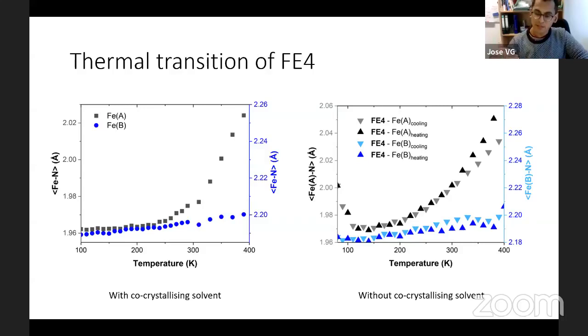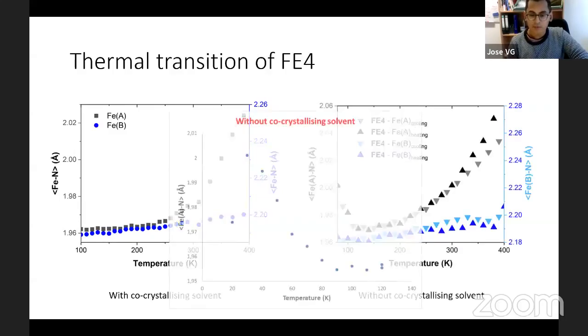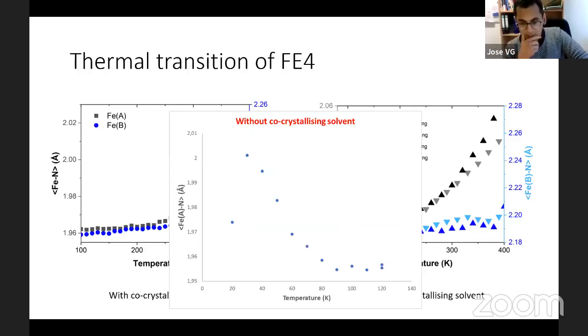So the material is passing again from low spin to high spin. You may say, oh, well, you stopped at around 80K. Yeah, that's true. But recently, last October, I had the opportunity to go to the synchrotron here and make the experiment below 80 Kelvin. And as you see, below 80 Kelvin, the reverse process from low spin to high spin is taking place again. This, to me, to some extent, contradicts what we know about spin crossover complexes.